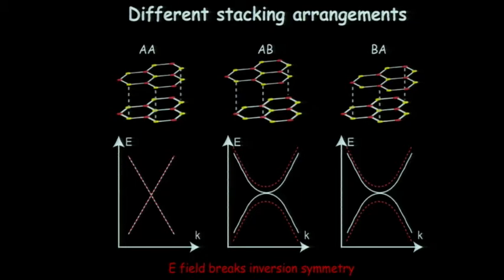So that's these dashed red lines. And the strength of that band gap just depends on the magnitude of the electric field. However, in this AA stacked region, when you apply an electric field, nothing really happens. You remain still in the same dispersion relation. There's no band gap opening. And so we're going to use this fact that we have different behavior with electric field to try to induce new topological states in the graphene.